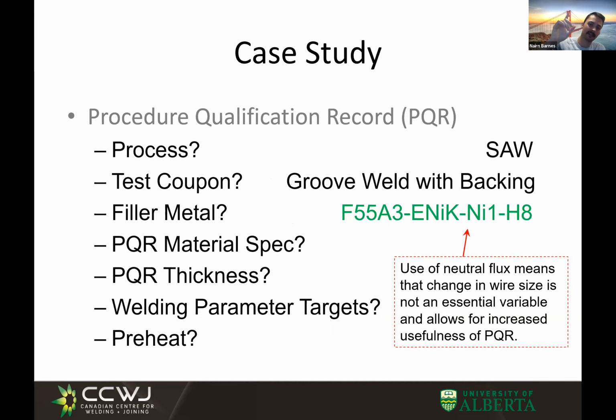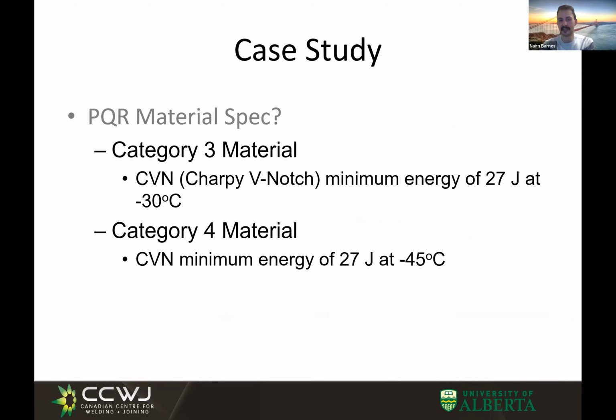So we have our process selected, essentially our sample. We know what it has to be. We've selected our wire and flux combination. The material, this is again one of those things of future proofing, where we're going to select our material. We know that based on this category 3, within the Canadian Welding Code, it's defined what that value actually is. So category 3 material needs to meet a CVN requirement of 27 joules, and the sample is going to be tested at minus 30 degrees C. So the sample is brought down to minus 30 degrees C, and then a hit, and they measure that, and it needs to be at least 27 joules.